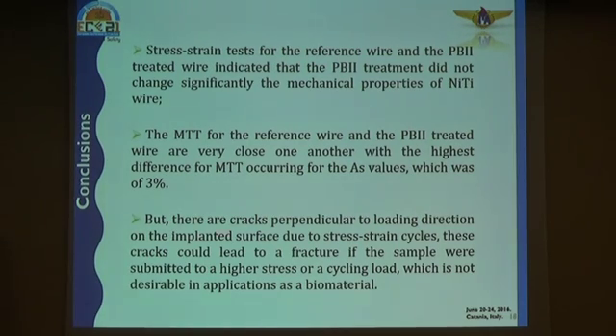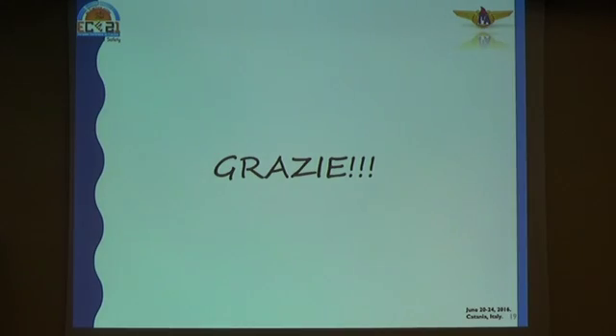But there are cracks perpendicular to the load direction on the implanted surface due to stress strain cycles. These cracks could lead to a fracture if the sample were submitted to a higher stress or a cycling load, which is not desirable in applications as a biomaterial. Thank you.